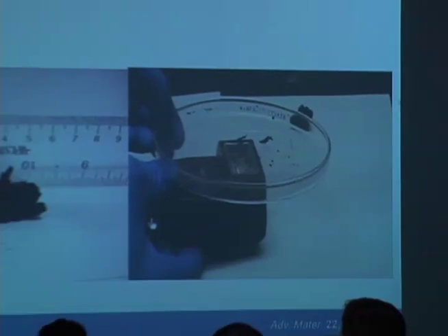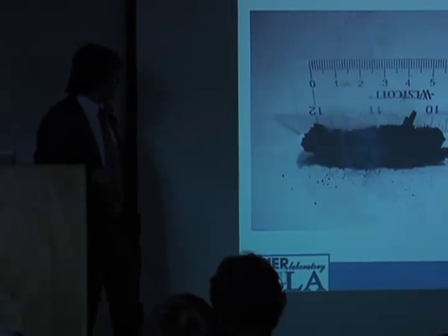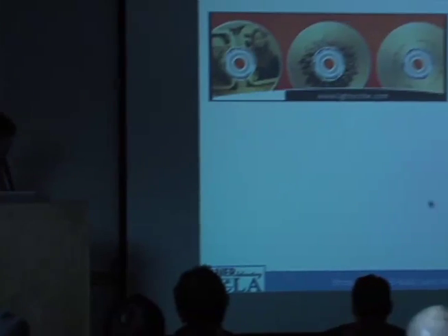Okay, so what are we looking at? Completely uncontrolled reactions, right? What's going on here, amazingly enough, it looks like it's burning, but it's essentially deoxygenating. So it's getting hot and giving off CO2. It turns out that we believe this process is exactly the same. It's absorbing the light, converting it to heat, and blowing off CO2. And when we're done at the end of the day, we can actually control this using a technology called Laser-scribed. So let me show you what that looks like.